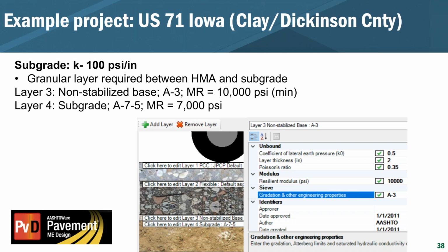So I selected a non-stabilized base for that 3rd layer and used the worst possible soil classification that I could, which was an A-3 under the non-stabilized base layer, and then the worst possible resilient modulus that you could use for an A-3. So that was 10,000 PSI. And then for the subgrade, that's where I tried to make things up. So for this, I used that 3rd layer, A-3, 2000 PSI, and I just made it a thin 2-inch layer. So that stiffness was only for a small thickness of a layer.